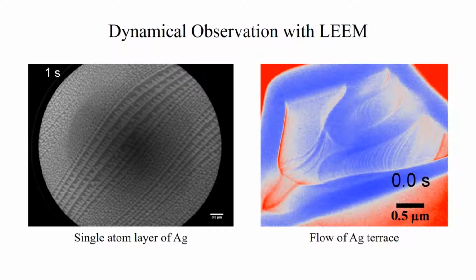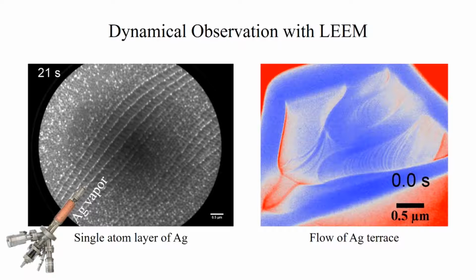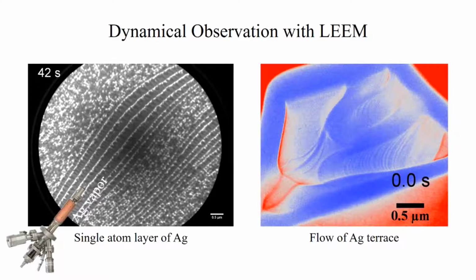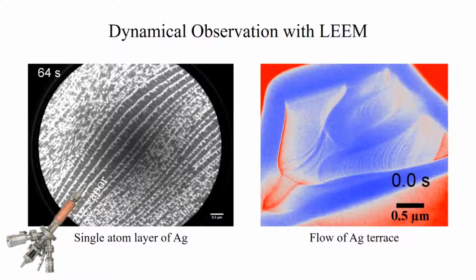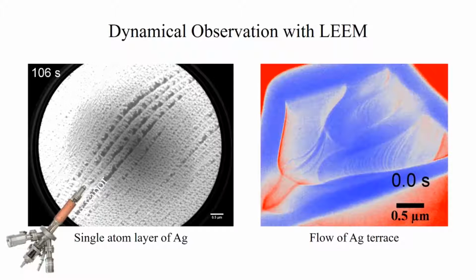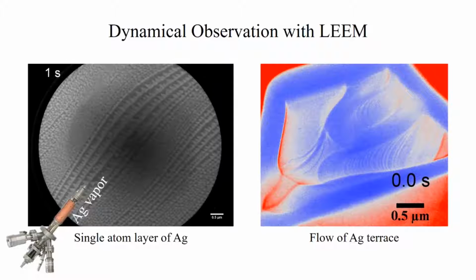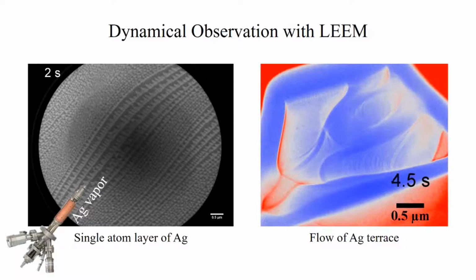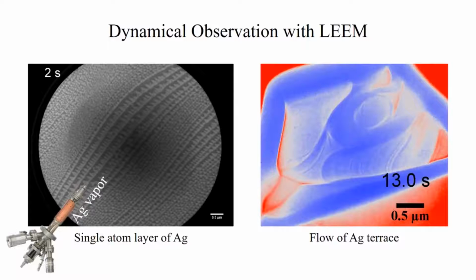clean silicon substrate. For example, in the first movie, we can image how the first one-atom-thick layer of silver atoms grows on a silicon surface with 1-1-1 crystalline orientation. The first layer is a wetting film on top of which nucleate three-dimensional single crystals of silver. The second movie is the nucleation of a silver island, where we observe crystal terraces flow in space as